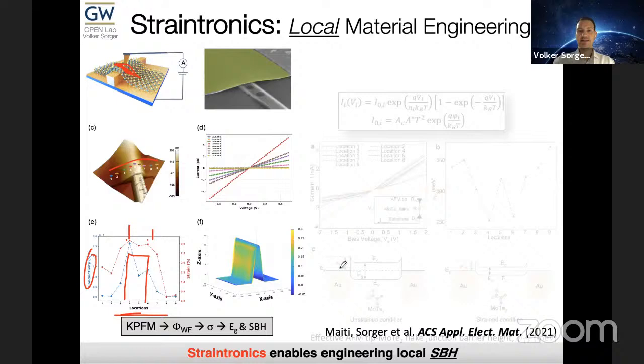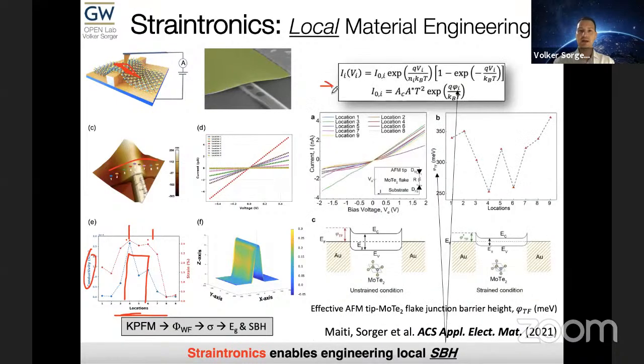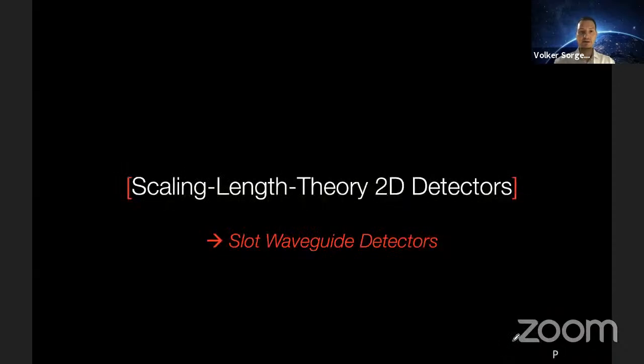And then when we perform some modeling of these functions, this current, we can extract this phi. This is the actual work function. So we can plot the work function as a function of spatial location. And notice, this allows us to tune the Schottky barrier height. So straintronics not only allows us to tune the mobility and the band gap, but also the Schottky barrier height. So it's a very powerful tool. And this work has just been accepted this week, in this paper here.